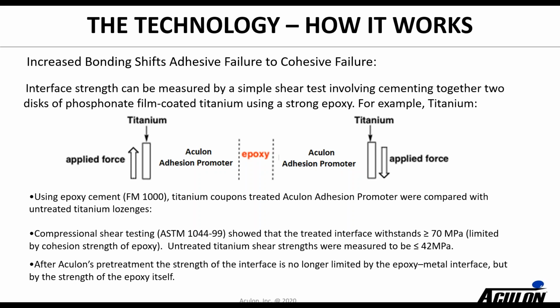So this is a good slide to show some tests that show just how strong our treatment really can be. This was a shear strength test that was done early on at Princeton University, where some of this technology came from, where we looked at bonding epoxy between titanium. We applied both an adhesion promoter as well as just a control, and you saw a pretty drastic improvement of shear strength, and we got shear strengths up to 70 megapascals. For those of you in the adhesive industry, you know just how strong that is. It's pretty impressive. That's just done by an Instron, where you have two coupons, you glue them together, and then you apply force and measure that force.